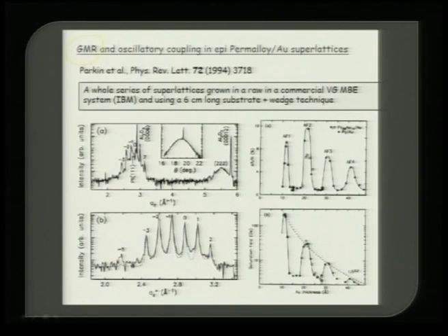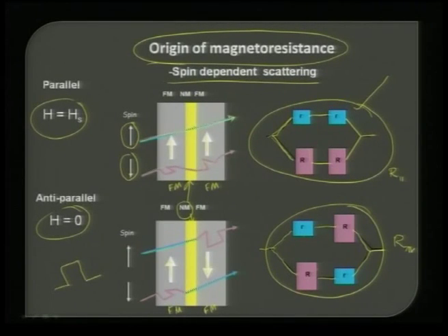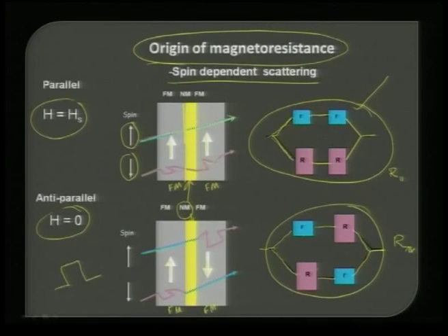One thing that we need to understand, if you want such GMR property to be there and if this is purely a spin dependent scattering, then I will come to the previous one once more. If this has to go through without scattering, this interface has to be very, very sharp, there should be no roughness. If there are physical defects also, scattering will occur. Therefore, you need to know how to make thin layers like this.